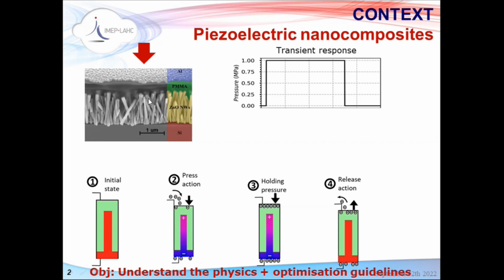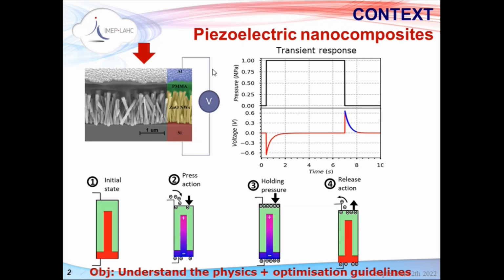So what we can do is to apply, for instance, a pressure on this material. What happens with this piezoelectric material? So imagine you apply a pressure on it. So I can represent it in here. If you put a pressure on this material, you will deform it, and because of the piezoelectric effect, the nanowires will deform, and then you will have a polarization inside, as I represented here. So basically, you have a positive part, a negative part, and because of that, you can immediately measure either charges here or a voltage, a peak of voltage, because this pressure is very sharp.